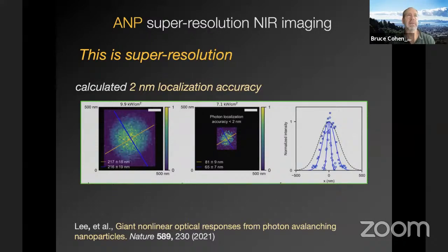That said, what we've shown and what others have shown is that if you're using a scanning technique, you are seeding. Your laser beam is not uniform, right? If your laser beam is about half a micron wide, it's a Gaussian, and so it's much more intense at the center. But there's quite a bit of photon flux on the edges of the laser spot. So if you're scanning over a sample, even if you're not exactly focused on a particular spot, you've started that rise time before you scan over it. So there are some tricks like that, where we might be able to seed the whole sample in 1064 light, but below threshold, and work to get faster rise times.